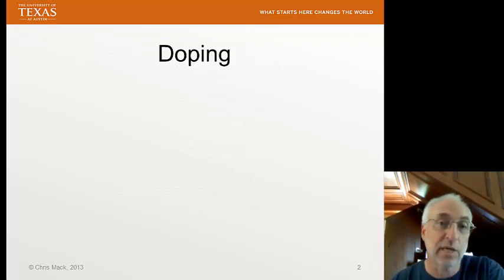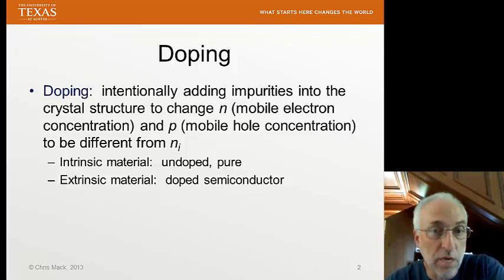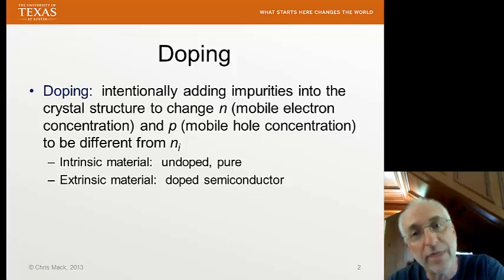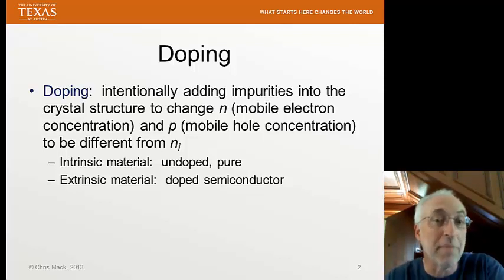What is doping in the world of semiconductor processing? Doping is intentionally adding impurities into the crystal structure of the semiconductor in order to change the mobile carrier concentrations. Remember, in semiconductors, there's two kinds of mobile charge carriers, electrons and holes. The concentration of mobile electrons is called N, concentration of mobile holes is called P. What we're trying to do with doping is incorporate an impurity of material other than, say, silicon for a silicon semiconductor into the silicon crystal structure so that we change the concentration of mobile charge carriers to be different from that of intrinsic material. Intrinsic material is pure material, undoped material. If you have some defects or some certain amounts of impurity that are very, very small, we still call this intrinsic material because we're not intentionally adding dopants.